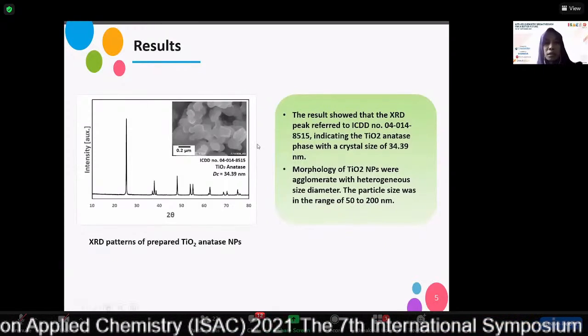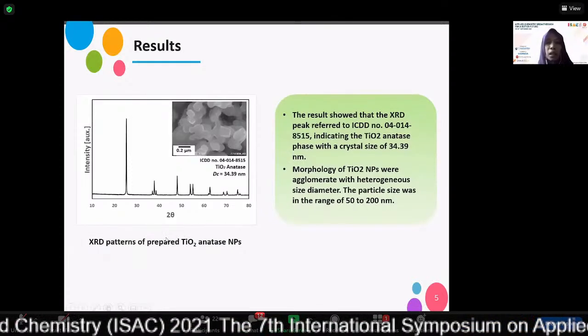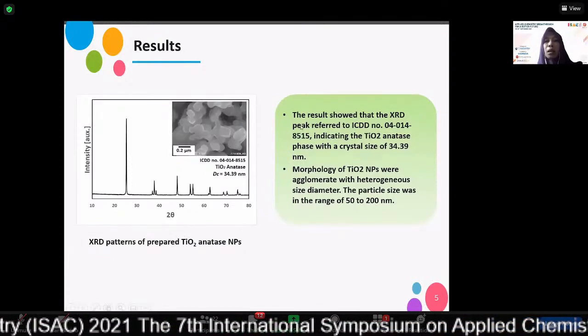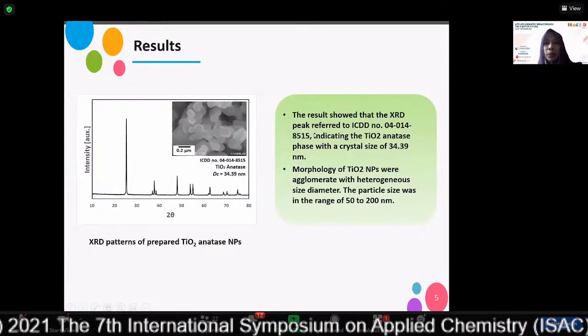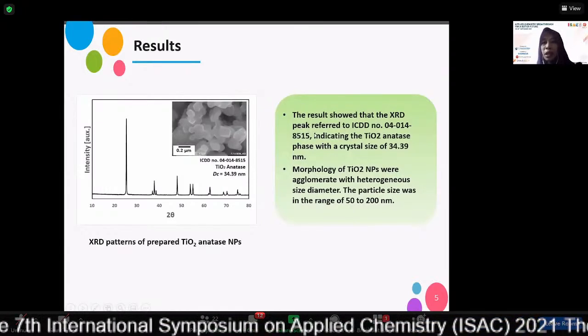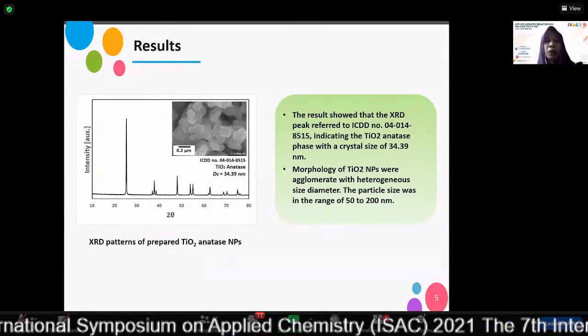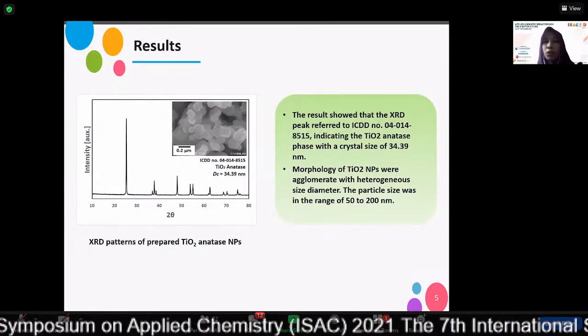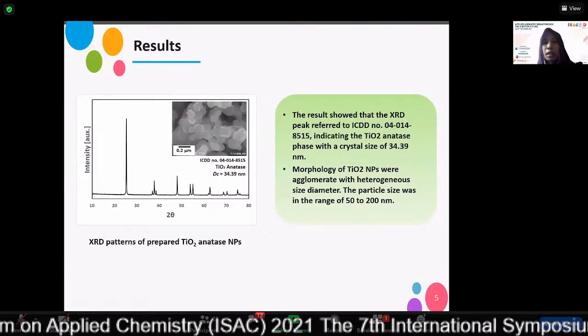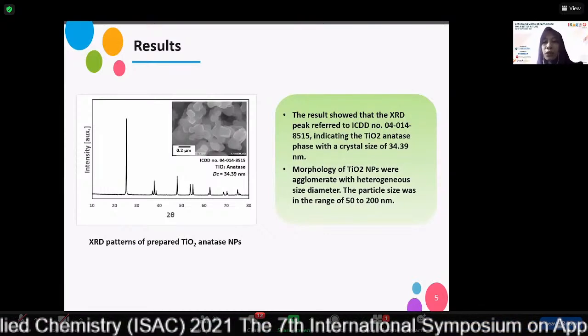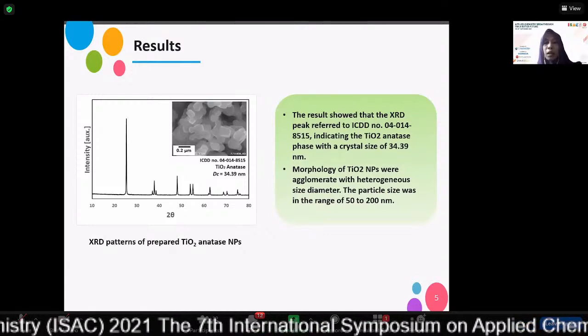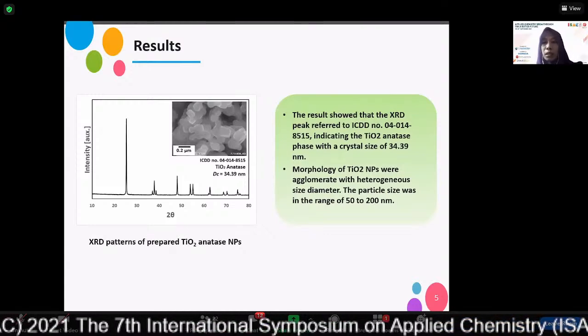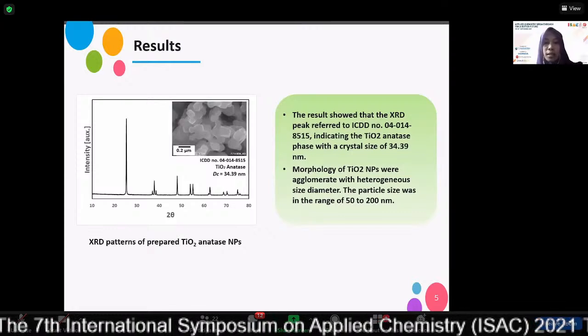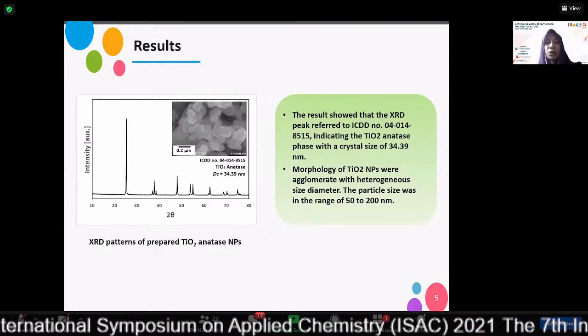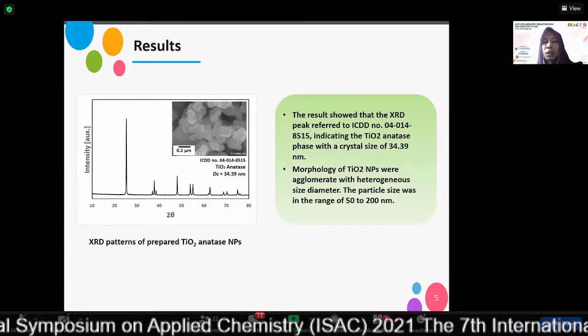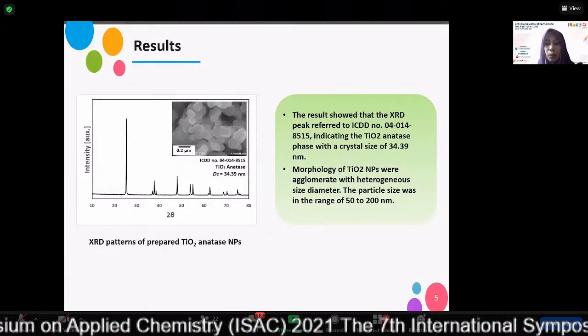experiment. First, this is the XRD pattern of the prepared TiO2 anatase nanoparticles. The result showed that the XRD peaks referred to ICDD number 04-014-8515, indicating the TiO2 anatase phase with a crystal size of 34.39 nanometers. And the morphology of the TiO2 nanoparticles was agglomerated with heterogeneous size diameter. The particle size was in the range of 50 to 200 nanometers.